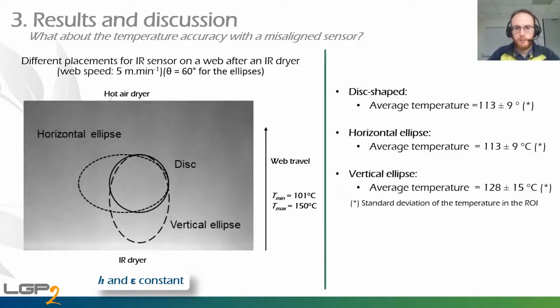For the disk shape and horizontal ellipse, we have an average temperature of 113 degrees, more or less 9 degrees. This is the standard deviation of the temperatures in the regions of interest. However, for the vertical ellipse, we have an average temperature of 128 degrees, more or less 15 degrees. So, statistically talking, we have no big differences.